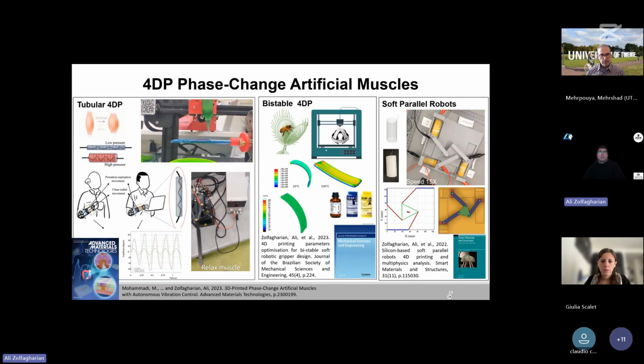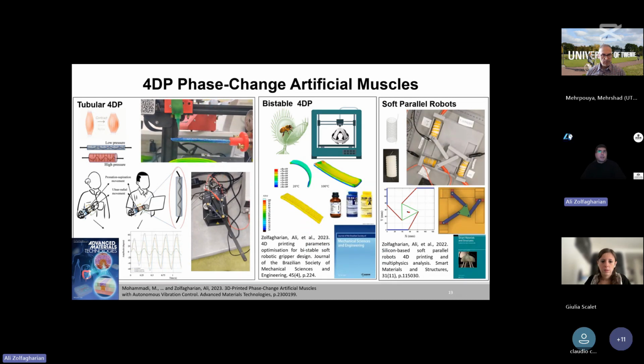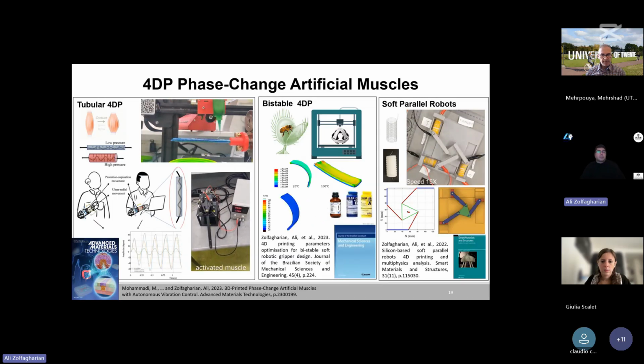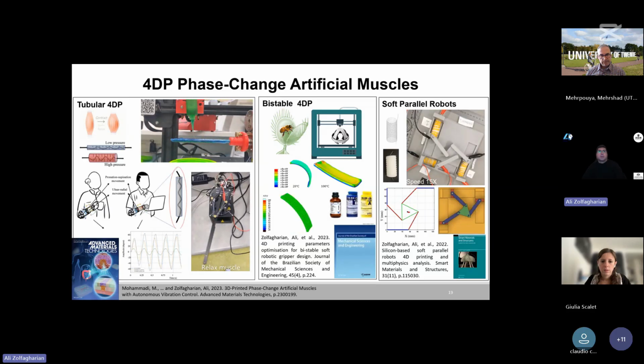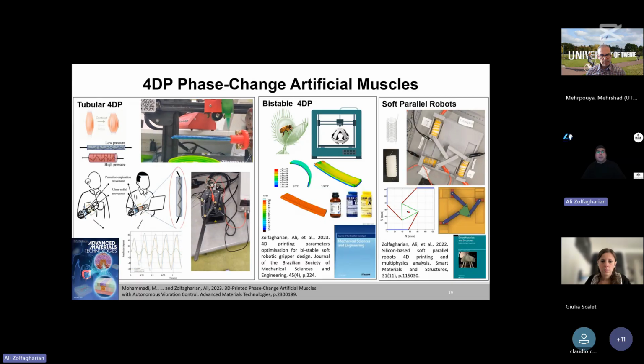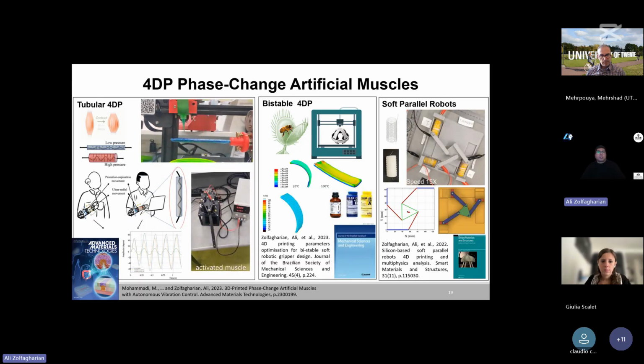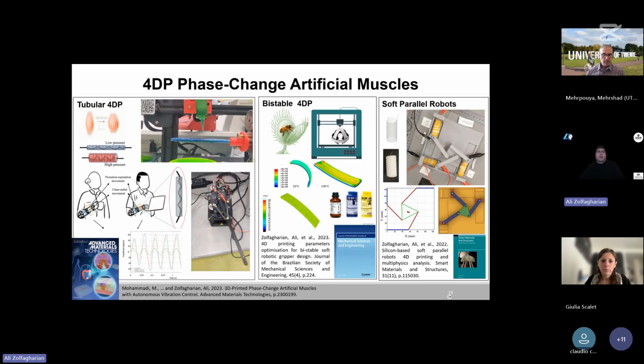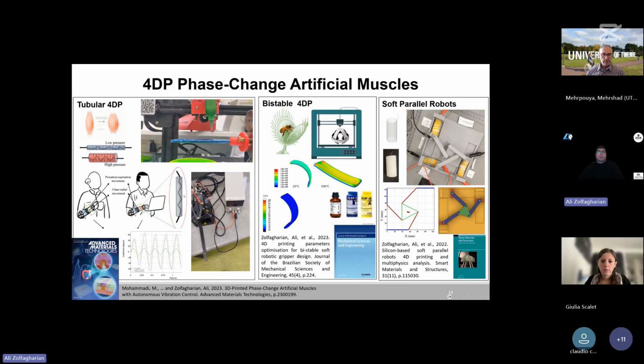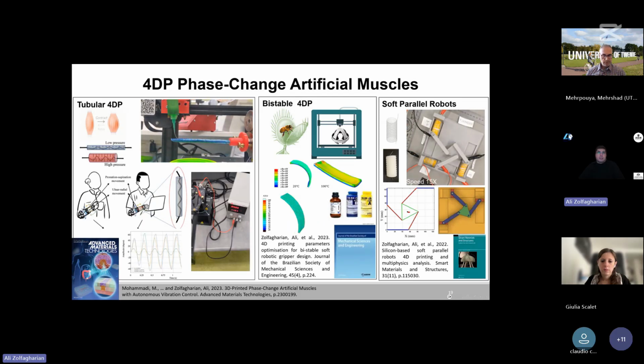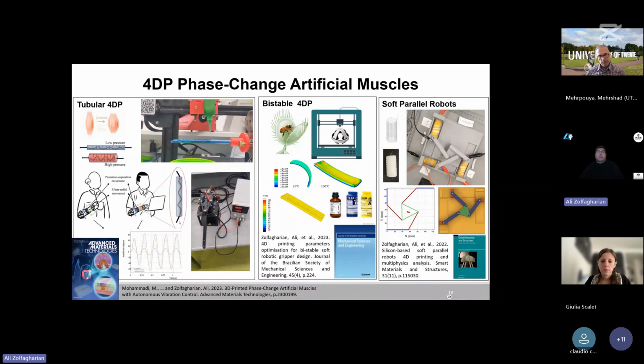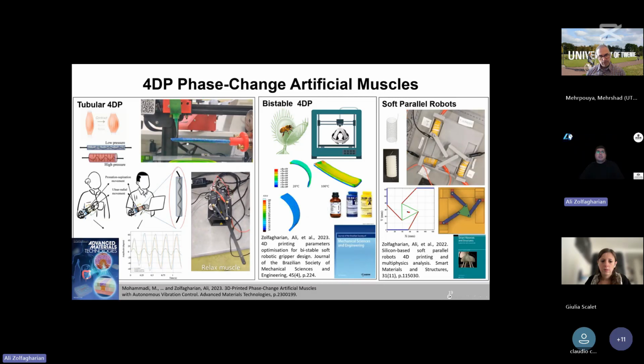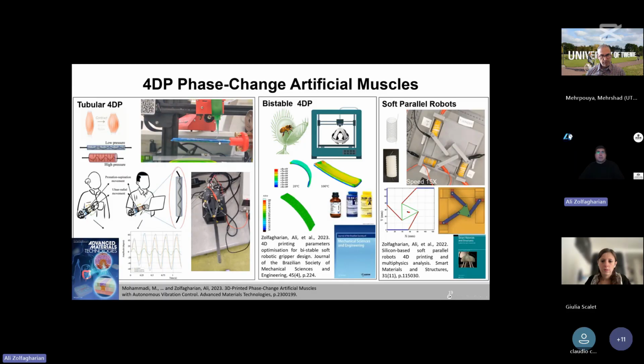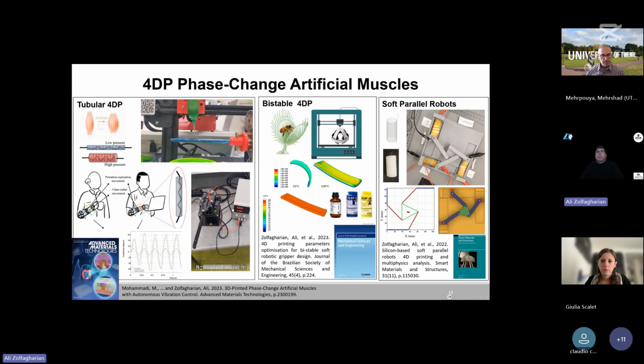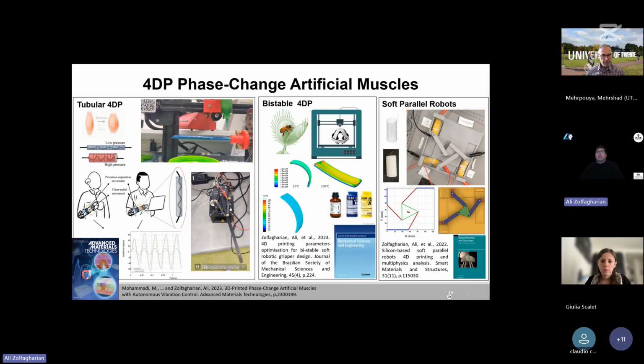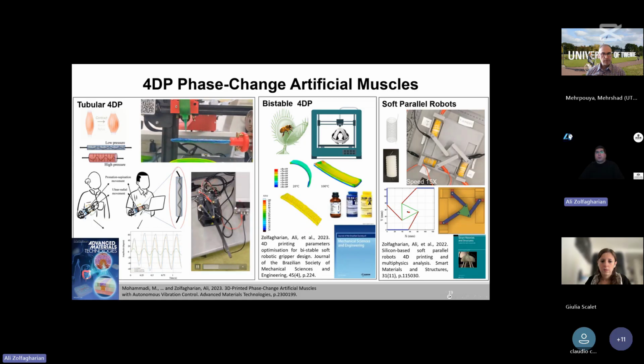Again, leveraging silicone, we mixed the silicone with ethanol, and the mixture of these two leads to some sort of actuation upon heating, because the ethanol reaches its boiling temperature and evaporates, but its bubbles are entrapped in the silicone, which leads to swelling after heating up to the boiling temperature. We used this characteristic and added a flexible fiber as a heater into the silicone, and printed that in the rotary printer, as you could see on the top left video. Then we use them for vibration reduction, and for changing the stiffness of joints in robotic applications.